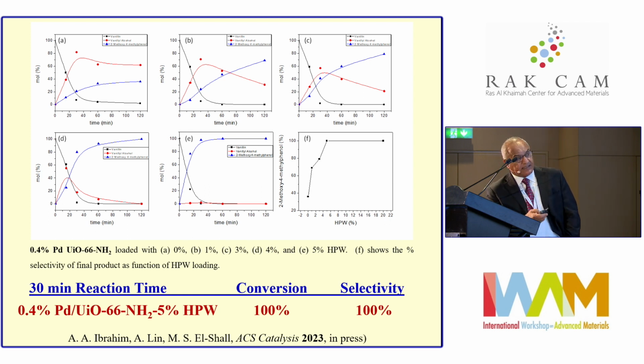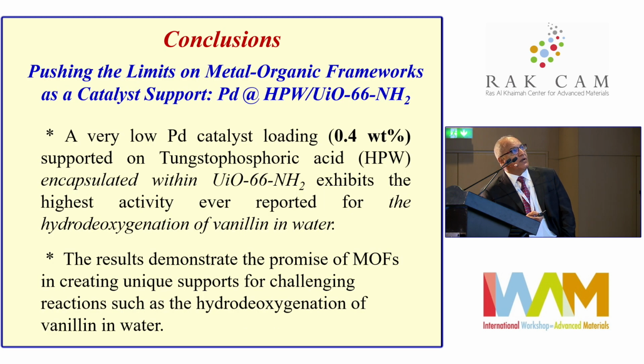So the third example that I wanted to cover for the vanillin hydrodeoxygenation, and I can conclude this part by saying that in the last case, where we incorporated solid acid within the UiO-66, very low loading of palladium catalyst can be used, 0.4 weight%, which is significantly low, using the tungstophosphoric acid encapsulated within the UiO-66, which shows very high activity.